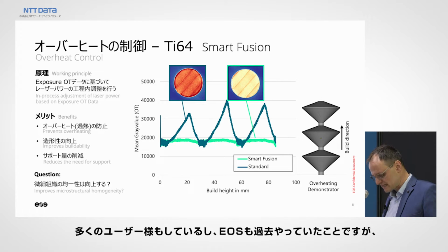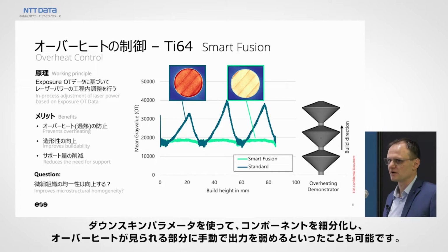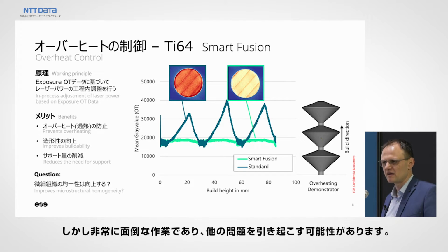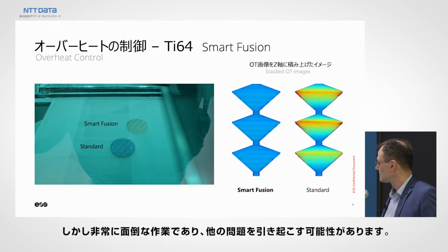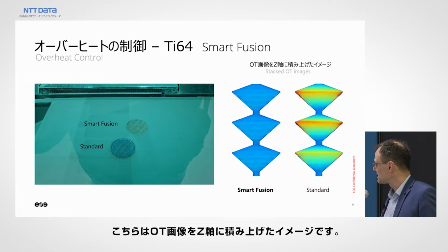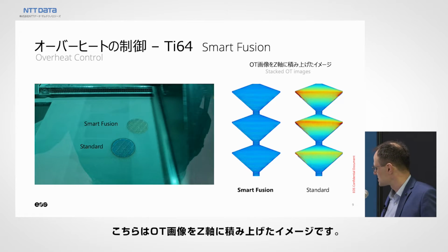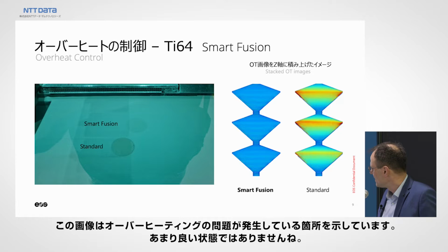So what a lot of customers are also doing, and what EOS was trying to do in the past, is to use downskin parameters, where you start to segment your component into areas where you apply in a manual way less and less power in areas that have seen overheating. But it's very cumbersome, laborious work, and it can lead to many other problems that I can address now in the next layer. You see that here also in the stacked OT images. So the infrared images or signatures really indicate where you have this overheating problem occurring in those regions.